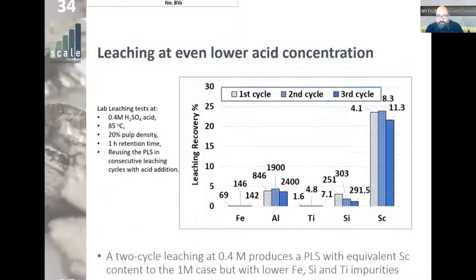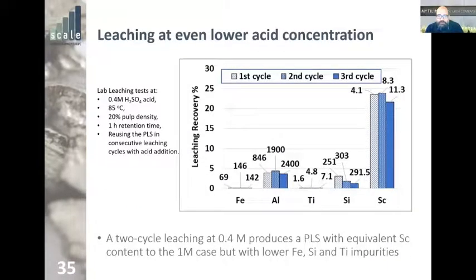So we had to think of ways of getting even less impurities in the solution. So we tried even lower acid concentration. And here's an experiment using 0.4 molar sulfuric acid, 85 degrees, 20% pulp density, 1 hour of leaching. But what we're doing, we are reusing the pregnant liquid solution that we produce after one leaching with some extra acid into a second and a third step of leaching.